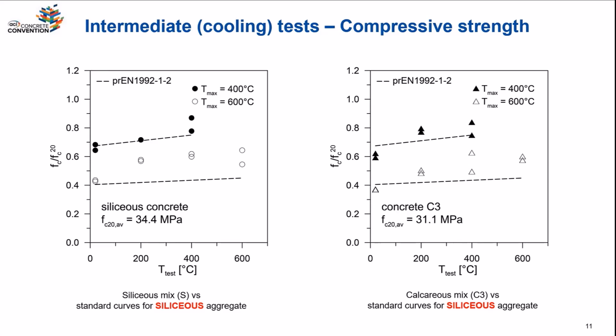That's true for all specimens. But you see that the trend while cooling is not really consistent, or we couldn't find any real logical trend there between the different mixes. So we always had further degradation of strength, but it was not a linear process.